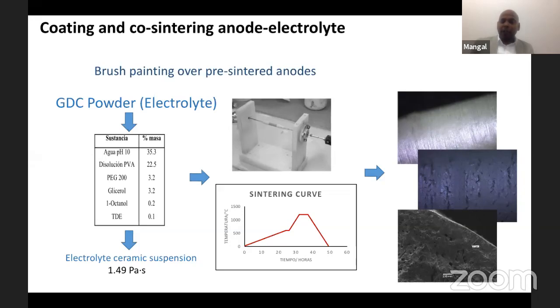So for that we need to prepare a slurry kind of material. Before, for fabrication, we prepared a paste, but now we need slurry. Slurry means a liquid kind of material, to spray like a paint spray for coating of electrolyte over the sintered anode. So for that we need the electrolyte also. We have to prepare it like a slurry. For the slurry also we need to formulate the composition, and you can see the composition on the left hand side, the percentage of each content of the material.